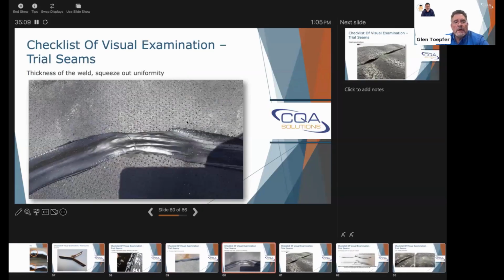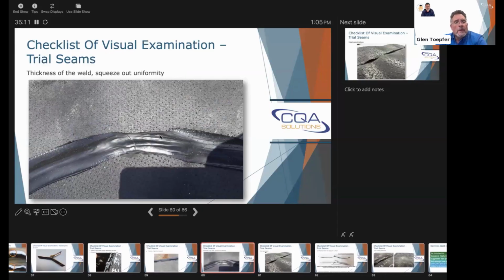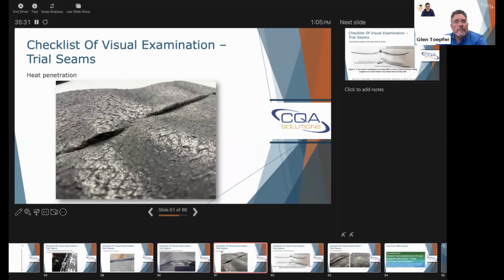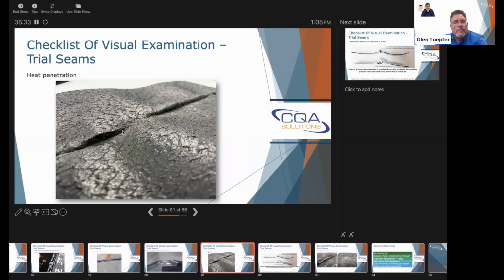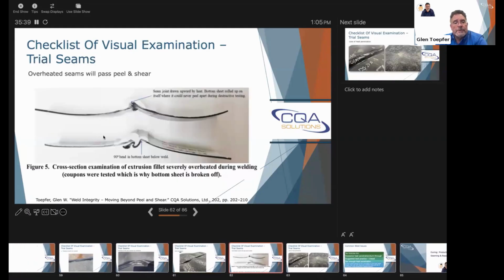Again, squeeze out uniformity. If they're having a problem with doing the squeeze out, this isn't a trial weld, but they're doing it round the bend here. They weren't getting uniform squeeze out. Their weld profile looks a bit off on this for whatever the shoe would have been. Your heat penetration, this is signs that there's separation. The material's separating there, so you're not going to have any strength there. So it's going to be an issue.